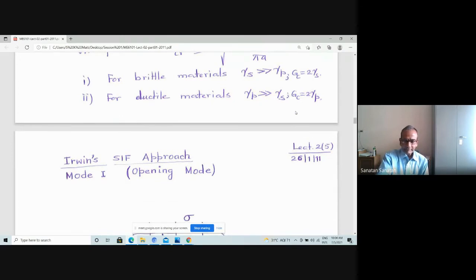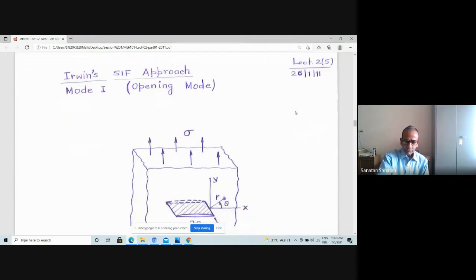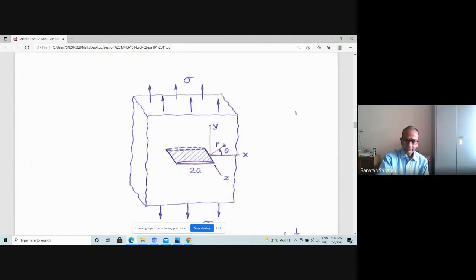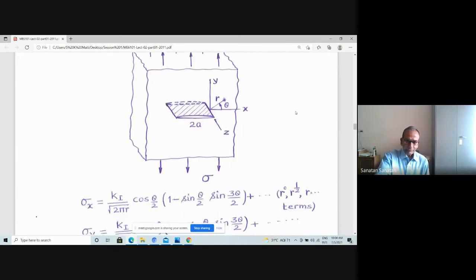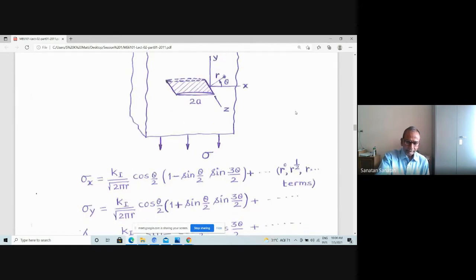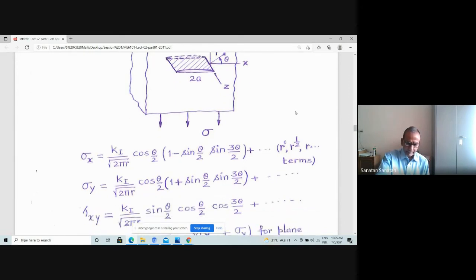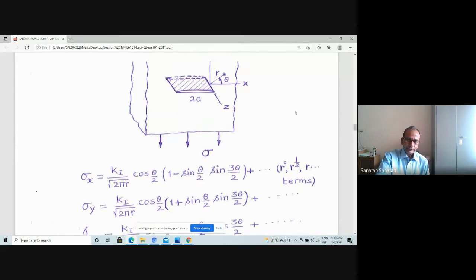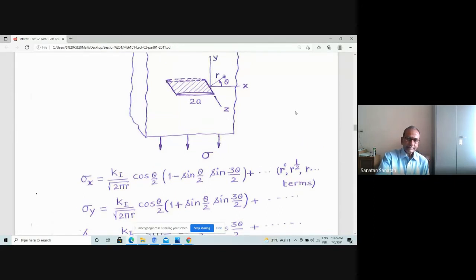And this was something which was answered by Irwin and his approach. So see this crack, imagine the crack to be like this, that you have a component which is loaded perpendicular to its plane, trying to open up the crack faces. So this is called the opening mode of crack extension. The crack faces are trying to separate, increasing the distance, and therefore this is mode 1. And he not only identified this classification, he was also the person who found that, since everybody says we must understand the stress field around the crack, he was able to solve the elasticity problem of a component with a crack in it and the stress field around it.